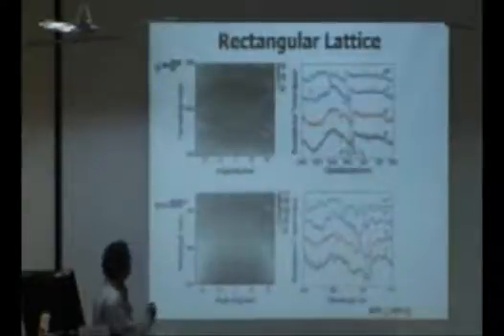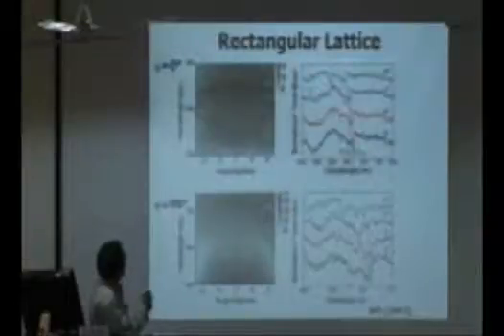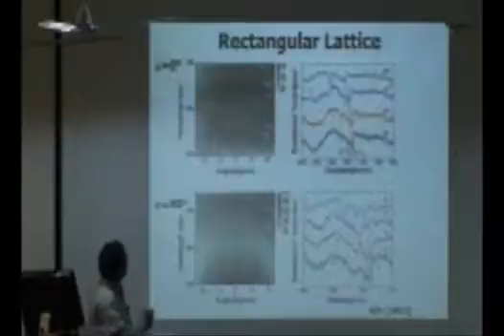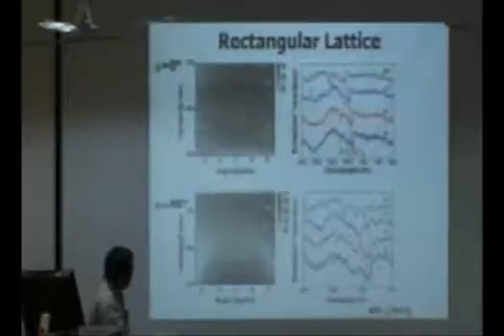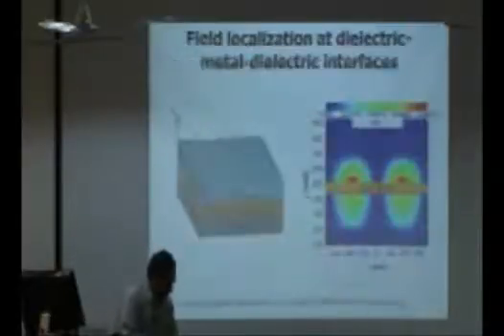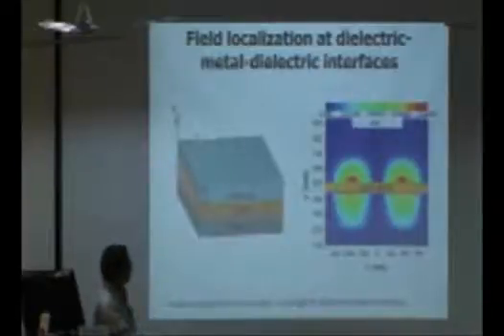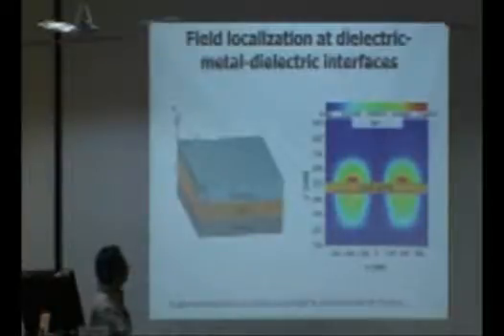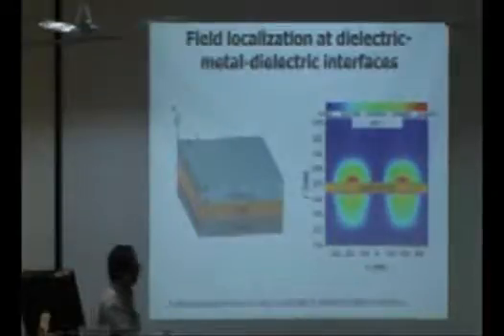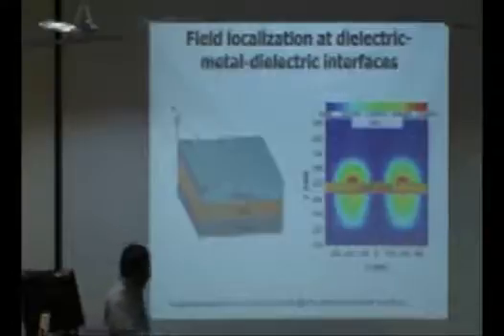Okay, what we show is that there is a flat, angle independent excitation of the plasmon mode. This is shown from minus 25 to plus 25 degrees, but you can go further. Okay. So the other interesting result from this is that clearly the FDTD simulations show that we have a localized field at the gold dielectric interface because of these grooves which we are making in the pattern. Okay, so this is a periodic structure which has been simulated, which shows that the field maxima are there at the interface, showing the plasmon excitation.